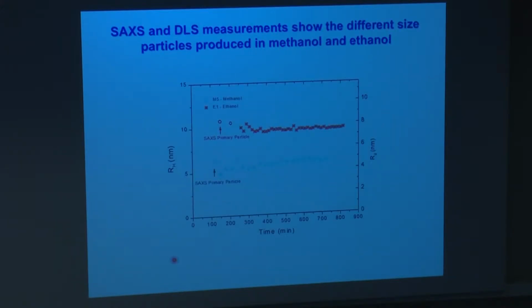These are some data showing the radius of gyration of the first particle that appears in ethanol and the first particle that appears in methanol, where the particle is bigger, almost twice the size of the first particle that's coming out in ethanol. And then the other data are dynamic light scattering results that measure hydrodynamic radius. And if you look at the data, the dynamic light scattering and the small angle X-ray scattering results are consistent.